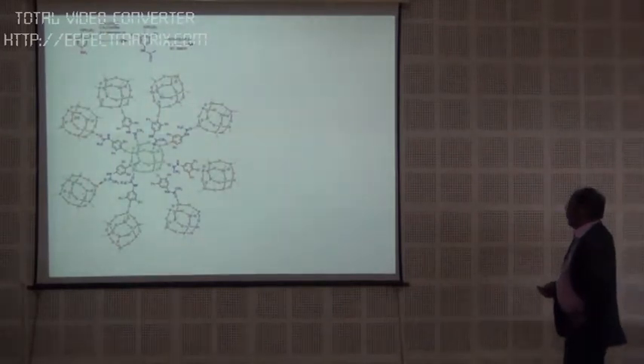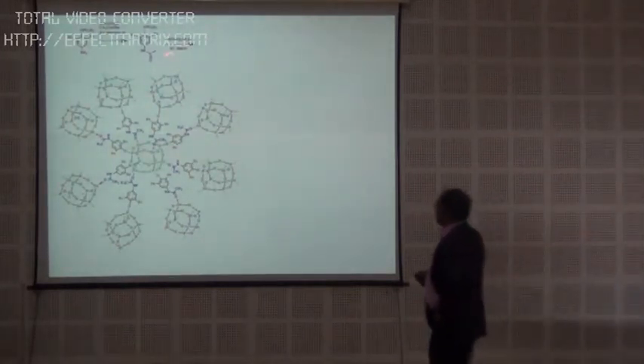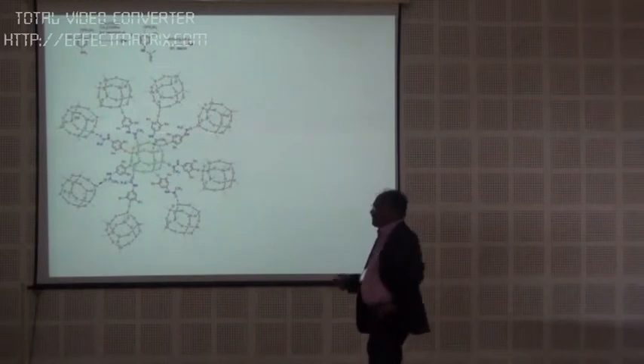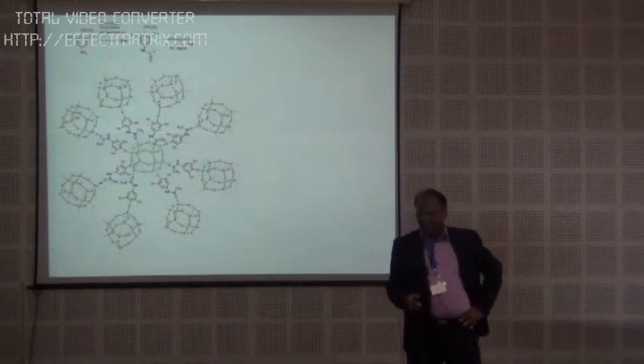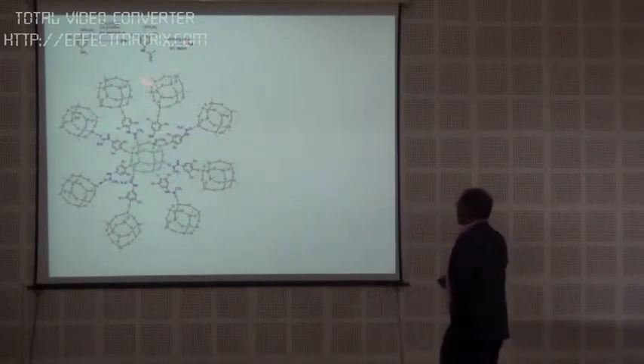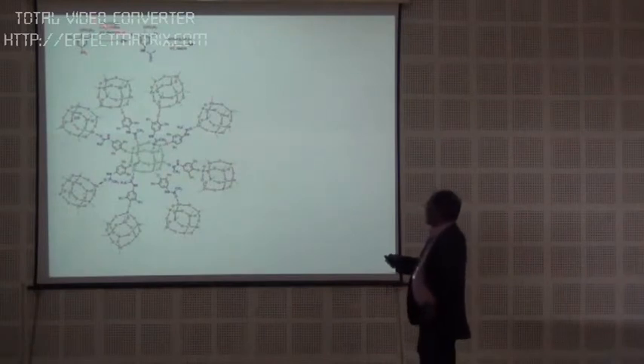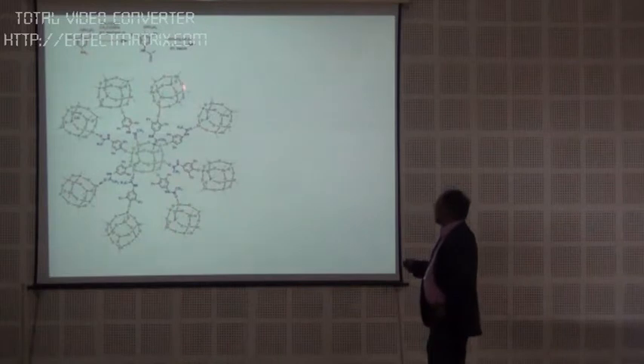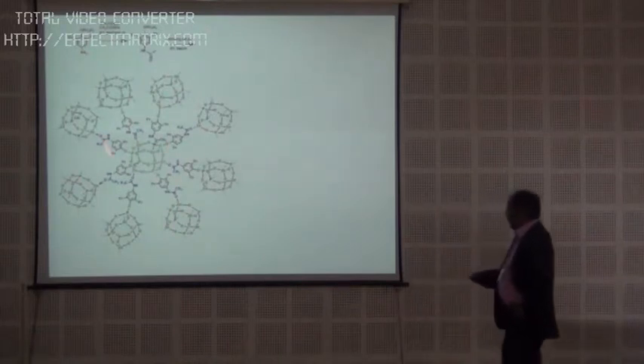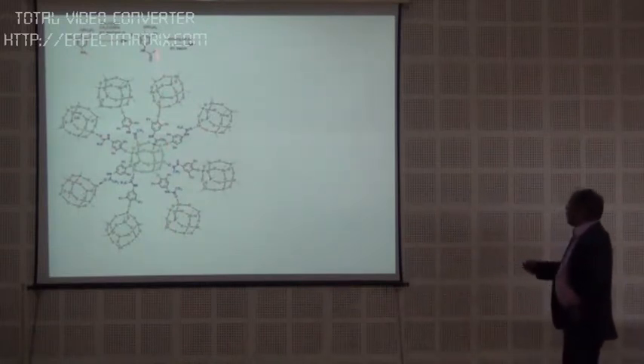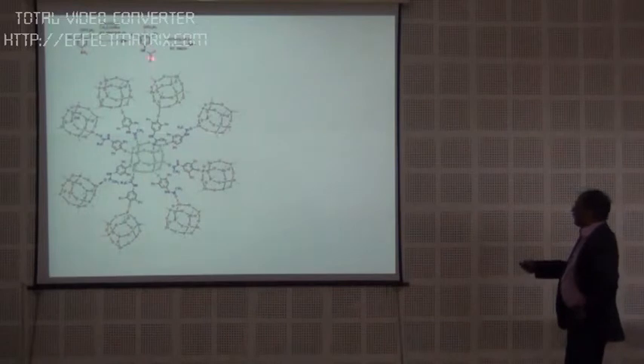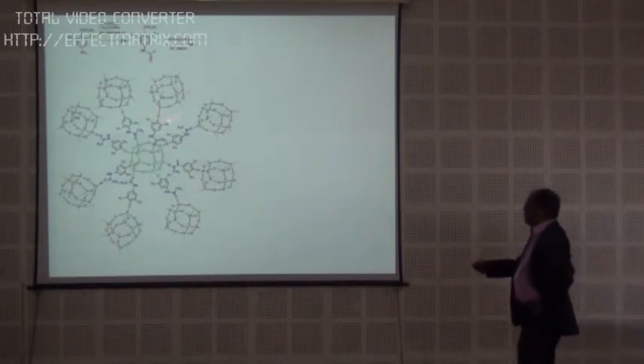So what was more satisfying, as I said, was when she did this organic derivatization. And she was actually having a problem with the solubility of the compound NH2. She wanted to protect NH2 or something. She put an acetyl group there by using acetic anhydride. But now, instead of going through several steps in one part, she could actually link 1 cubane to 8 cubanes. The PO3H2 part of the molecule actually forms the cubane, and the carbonyl that is hanging as a tail actually bites the nearest neighbor.